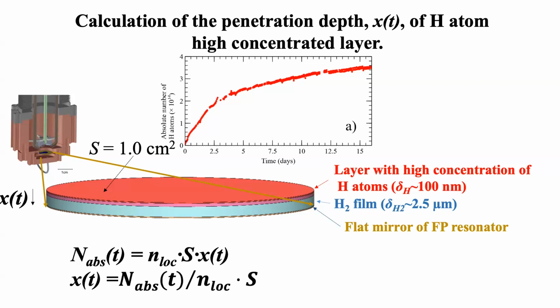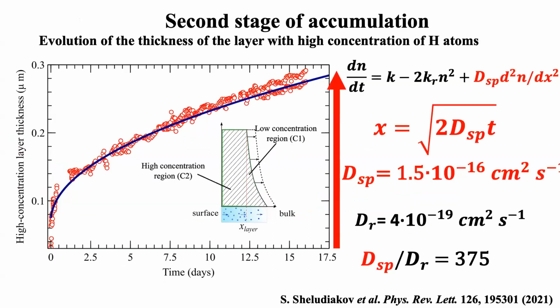And we can determine from this curve the penetration depth according to this simple equation. So we make the graph of the thickness of this high concentrated layer on time from the recalculation, and these are the red points.